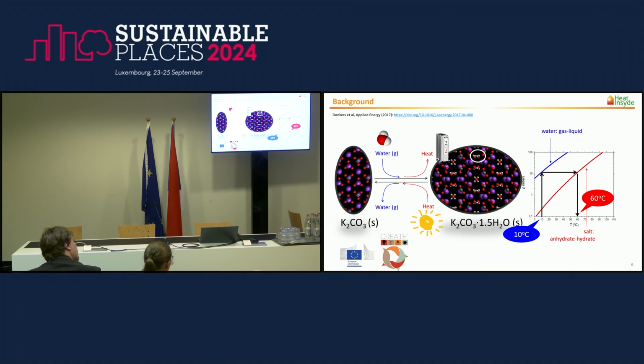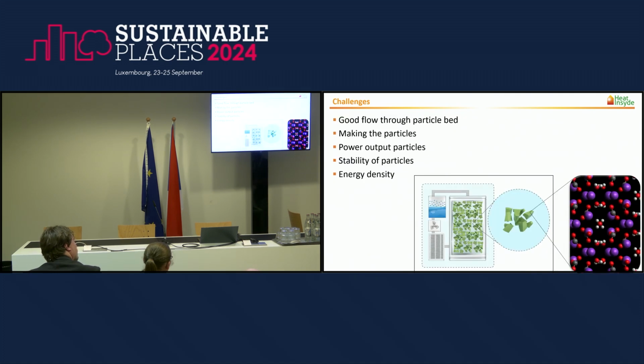Then you can generate, for example, 12 millibar water. If you bring that to this particular salt at max, and that's really the theoretical maximum, in reality it's always lower and never higher, you can generate 60 degrees Celsius there. But that's a theoretical upper limit. Now, this is a bit the principle. Now going to the challenges,